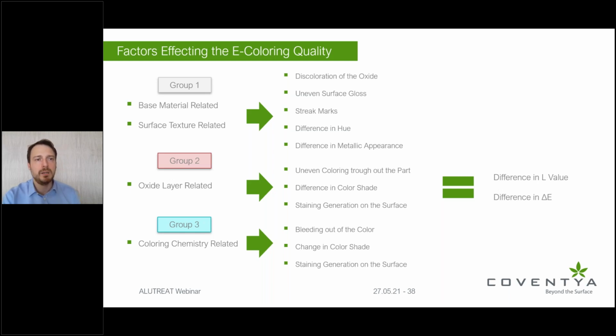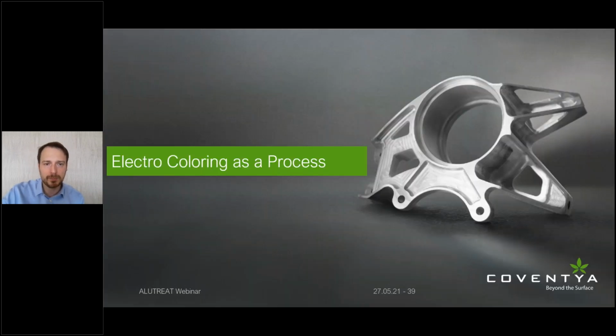The first group is related to the base metal. So the alloy, what type of surface treatment it has gone through, is it casted or forged? And then the second part is related to the surface texture, because these are basically determining how reflective your underlying metal will be. That will be eliminating your oxide layer and the precipitate. Secondly, is related to the anodizing and also coloring processes, where the transparency and the orderliness or homogeneity of the oxide layer will have a huge effect. And finally, the third group is related to the coloring chemistry.